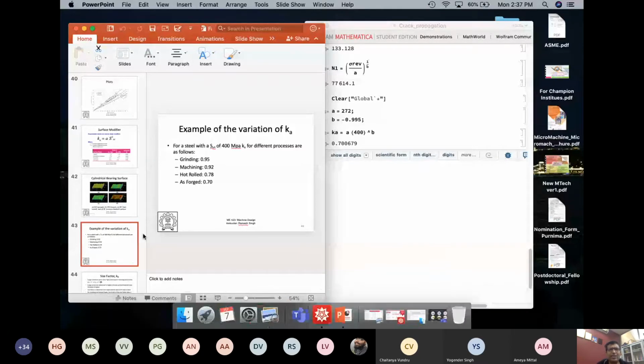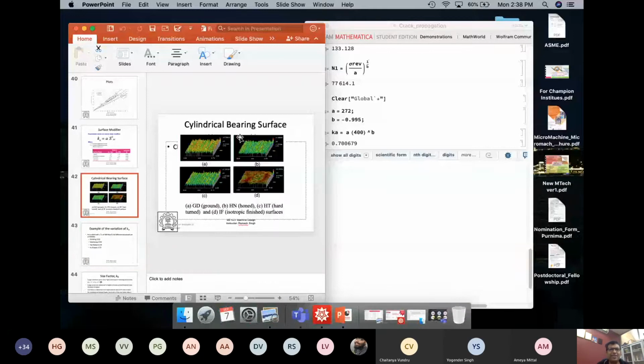You can look at some of the surfaces also. These are some bearing surfaces which I actually worked on, trying to characterize the functional response of them. Some of the surfaces which people use in bearings: ground, honed. There's some process called hard turned. Hard turned basically means that people harden the steel and then turn it with a cubic boron nitride tool, with a very rigid tool, so that you get a very smooth surface. As turned, the surface is very smooth, almost like a finished surface, so you don't do a secondary grinding.